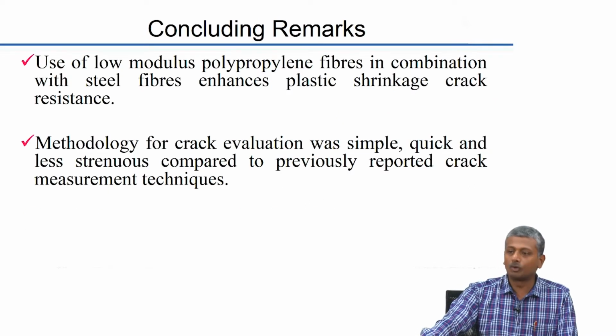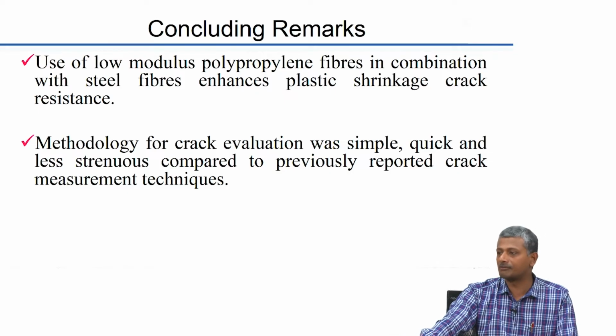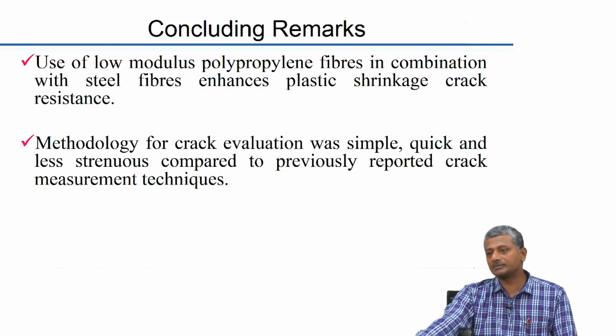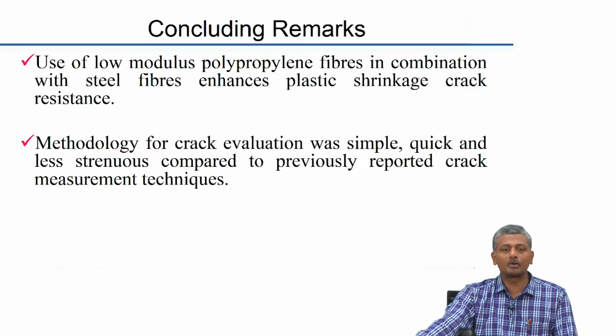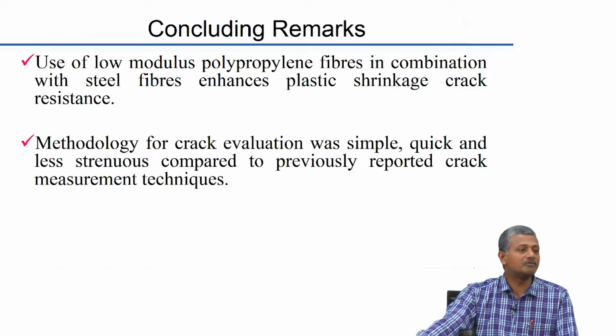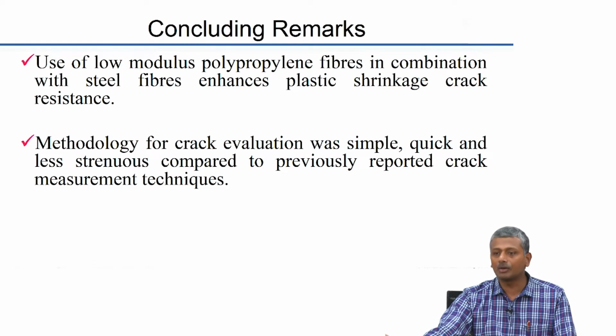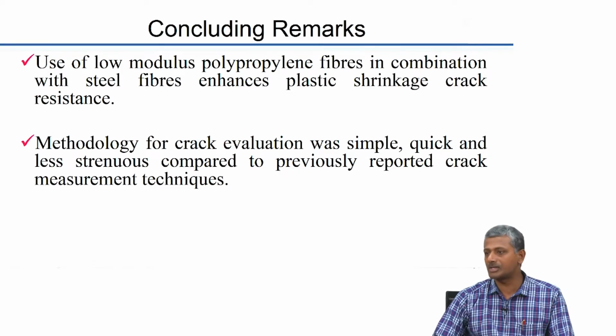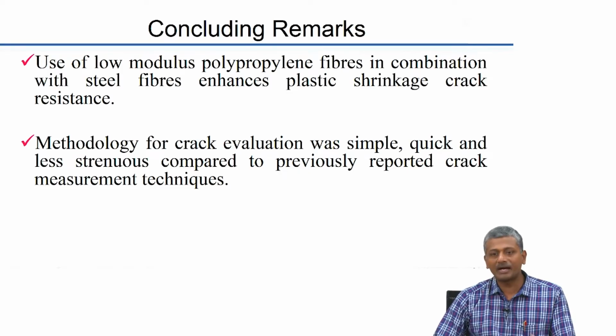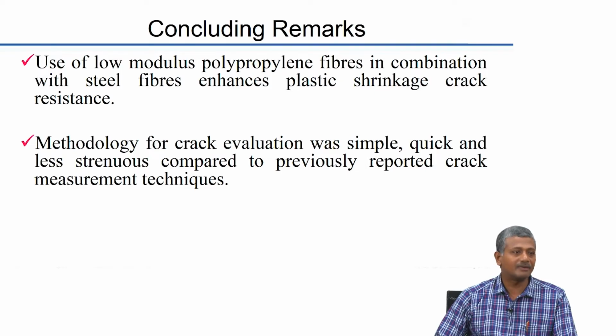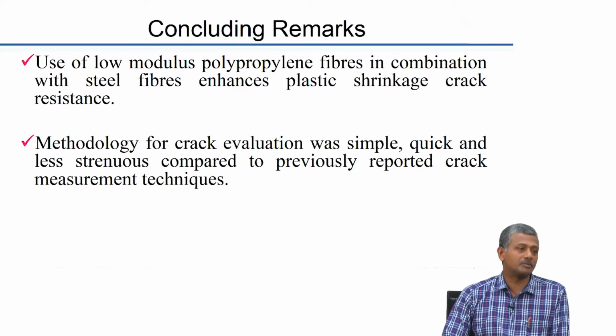So again, use of low modulus polypropylene fibers in this study added to the benefits of already putting in steel fibers. Of course, just using the low modulus fibers like polypropylene and polyester in the concrete may not be beneficial in the long run, because for hardened concrete characteristics like we discussed in the last chapter, you have to have the steel fibers present to have any significant post peak deformation behavior.